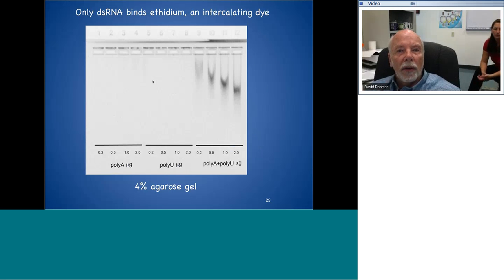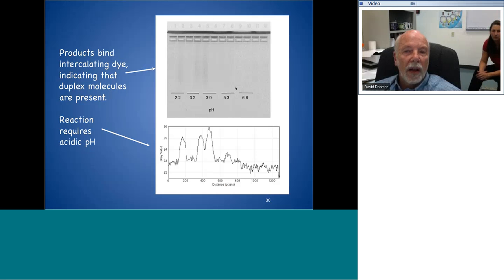This is very important. Only double-stranded RNA binds this intercalating dye called ethidium. Here's poly-A up to 2 micrograms in the gel. You don't see anything. Here's poly-U in the gel. You don't see anything. If you mix these together, let them form a double-stranded species, look at this. Now the ethidium intercalates into that double-stranded structure, and we can see the fluorescence. The reason that's important is our product strand, under these conditions, picks up ethidium bromide.